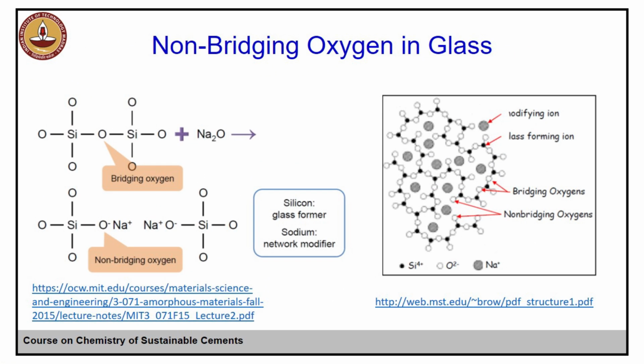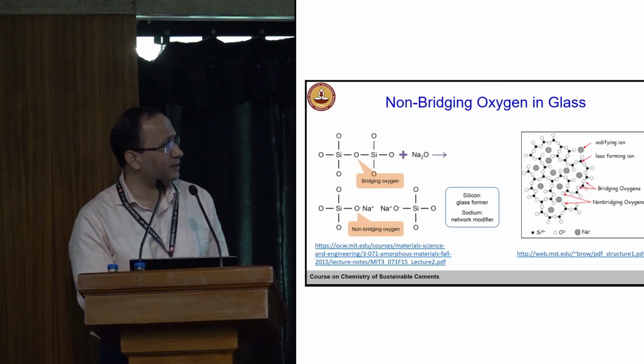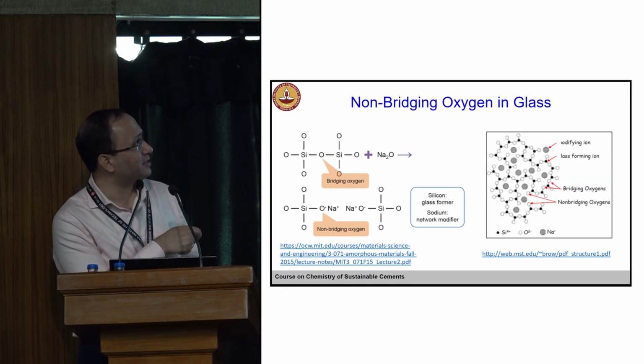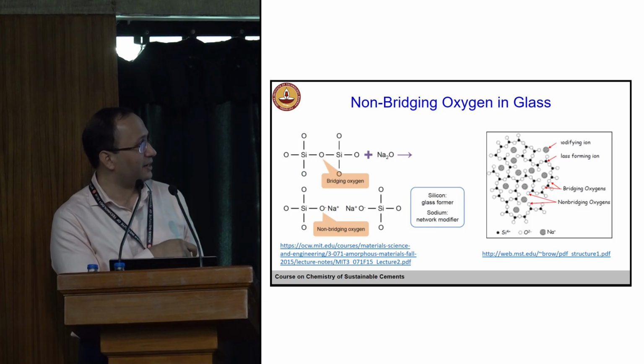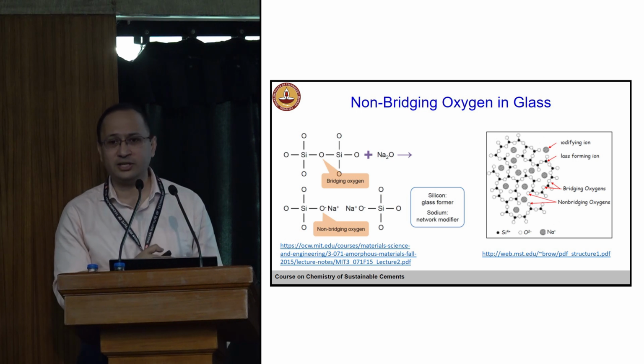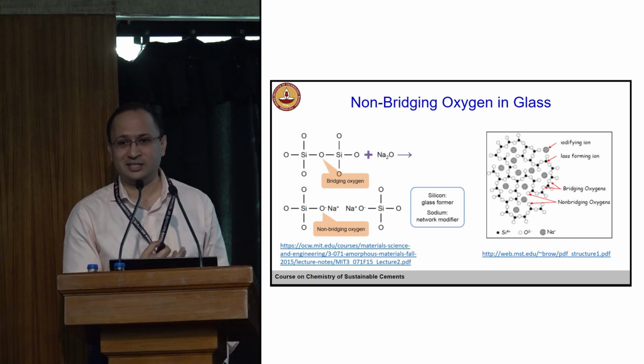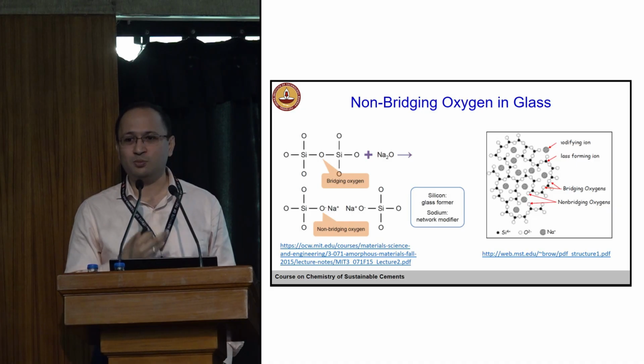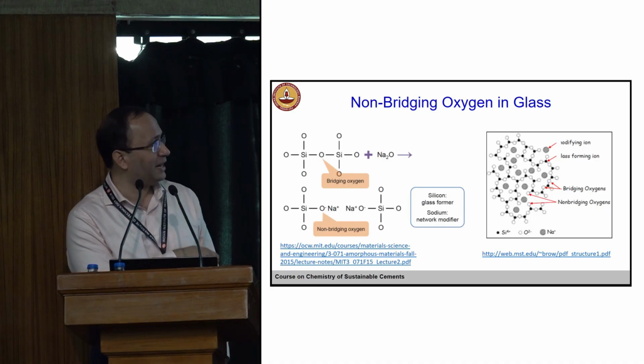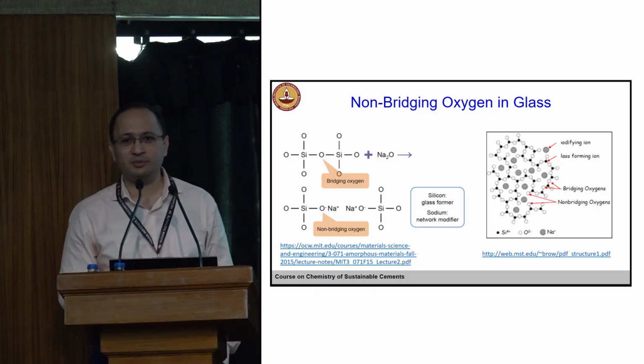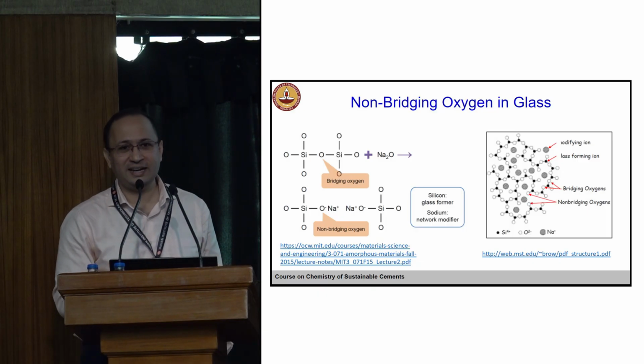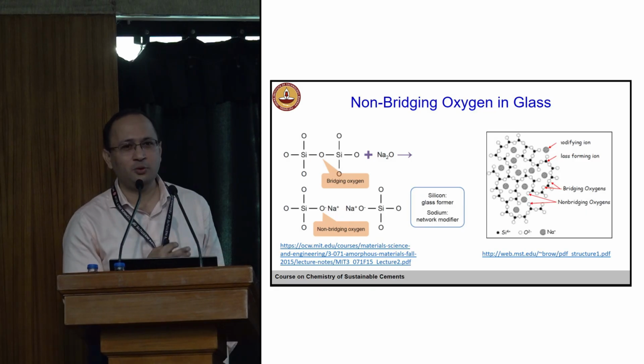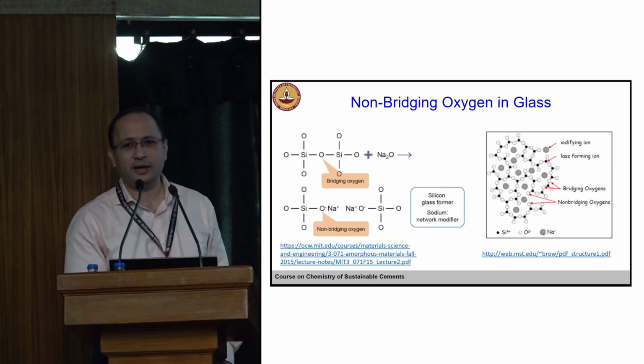So what drives this reactivity? In this case, you can see you have these network modifiers. You have bridging oxygen and non-bridging oxygen. Let's say in this case you have bridging oxygen, and here you have non-bridging oxygen. Imagine that if you have more non-bridging oxygen, then you have more defects in the system. If you have more defects in the system, then it's more reactive. So if you can estimate the fraction of non-bridging oxygen in your system, it should be able to tell you, reasonably well, the difference in reactivity.